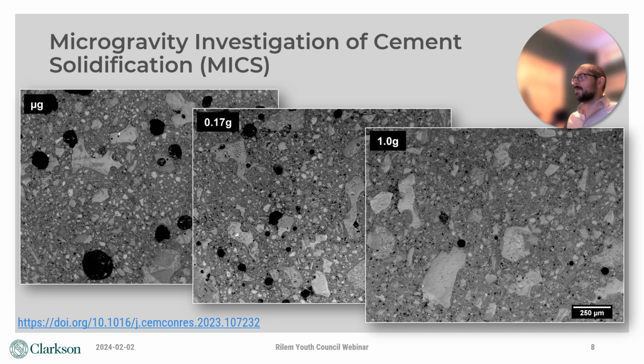We need phenomena like buoyancy to help air bubbles settle out of the fresh concrete, and these effects are diminished at lower gravity. Of course, we know that air voids represent stress concentrators inside the microstructure, and we know that these macroscopic air voids greatly weaken the strength of the material. But they also make it more permeable, which presents another problem for structures that need to be pressurized. And this is yet another challenge that we'll need to work to address.